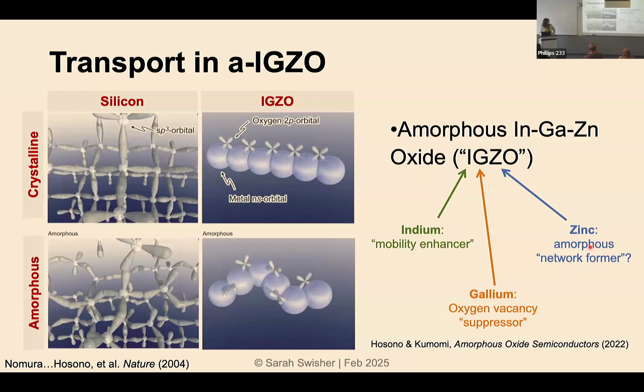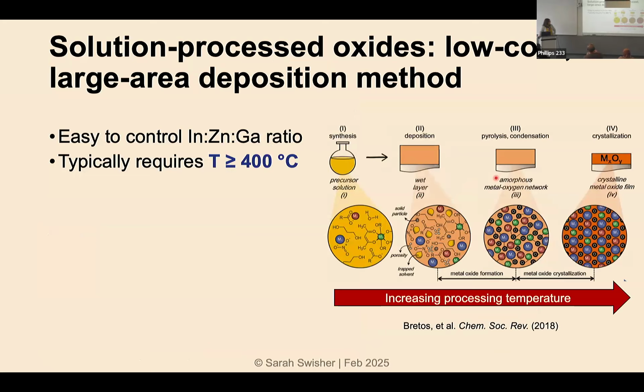And then zinc, it's a little bit less clear exactly. Zinc can play the role of the suppressor as well, but it also helps to make sure that the network remains amorphous, so that we don't crystallize, which we really don't want these materials to do. And so by including either gallium or zinc, we can control the carrier concentration, so we can actually have devices that turn off, and we can avoid crystallization as well. So playing with the different ratios of these materials is one way that we can really explore how to optimize their performance. And one way that we do that in my group in particular is using solution processed oxides.